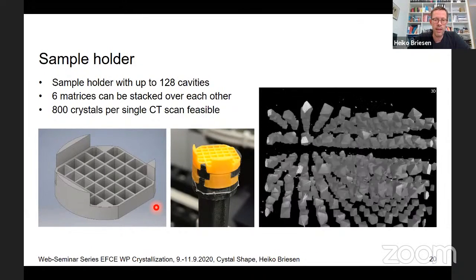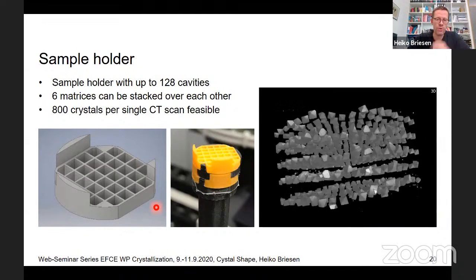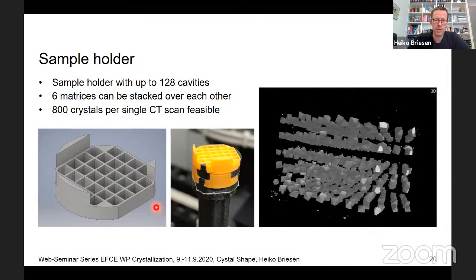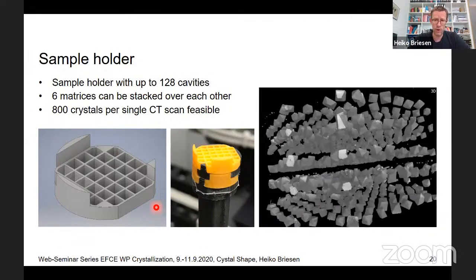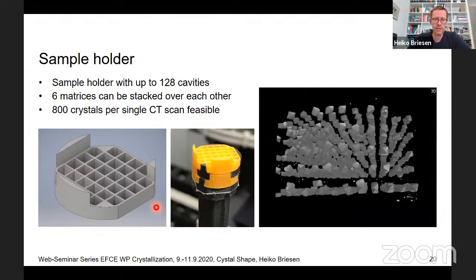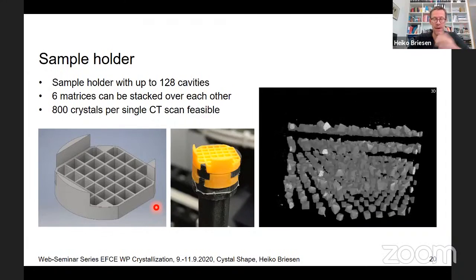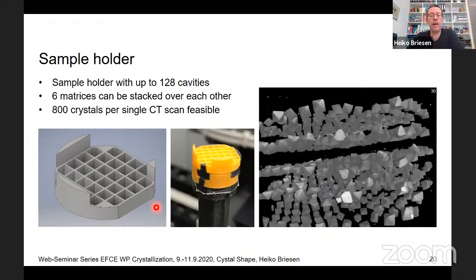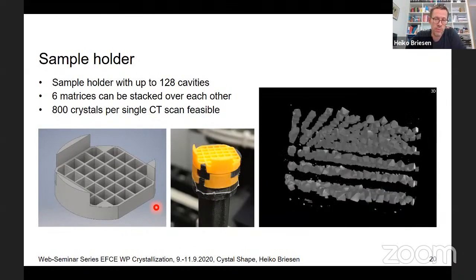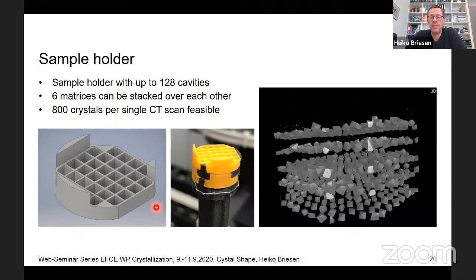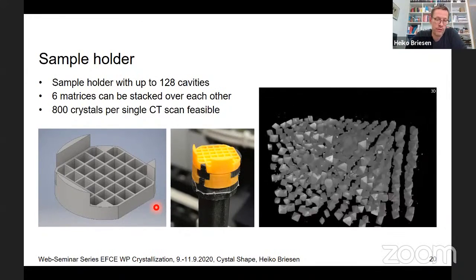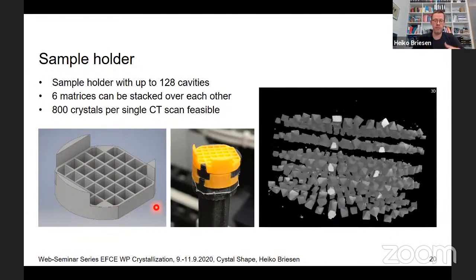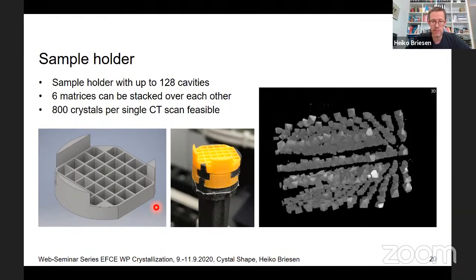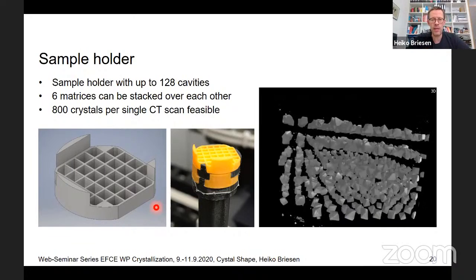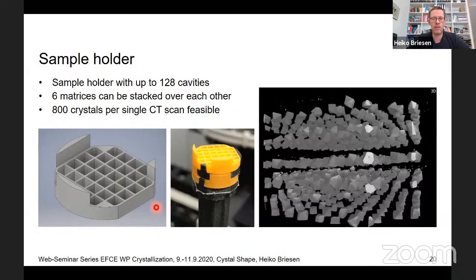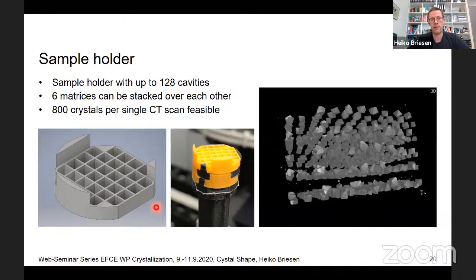This is, for example, a CT scan of a large data set, and you see here again our go-to crystals, the potash alum crystals, which are nicely rotating and can be easily separated from each other. There's no problem with that. We have good contrast between the particles and the surrounding medium because they're in air, and we can also have quite a large number with one single CT scan. Before this question comes, one CT scan is typically in the order of several hours. It depends on the resolution you're looking for. Now we are at a status where we can look at many crystals, and we chose a process here which did not produce much aggregation, so we're looking only at the crystal growth.